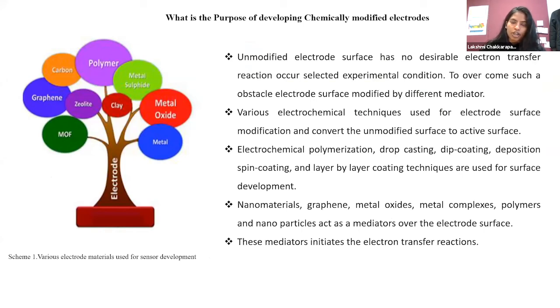And the thing is, we use many kinds of polymer and metal complex nanomaterial to develop the electrode surface, because an unmodified electrode surface doesn't have desirable electron transfer. So that's why we want to develop the electrode surface, and different kinds of methods are available for this technique, like improving the surface. For example, electropolymerization, dip coating, drop casting, deposition, spin coating, and layer by layer coating. The nanomaterial, graphene, and metal complex, this kind of mediator, develops the electron transfer reaction between the electrode surface and the solution, like the electrolyte with analytes.